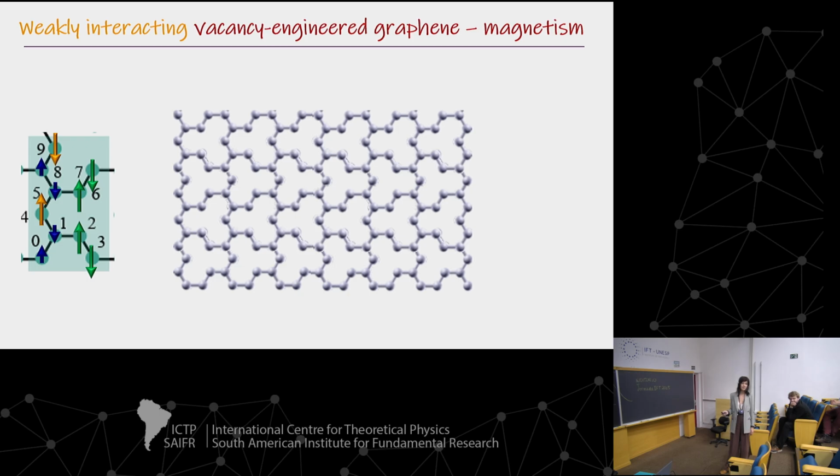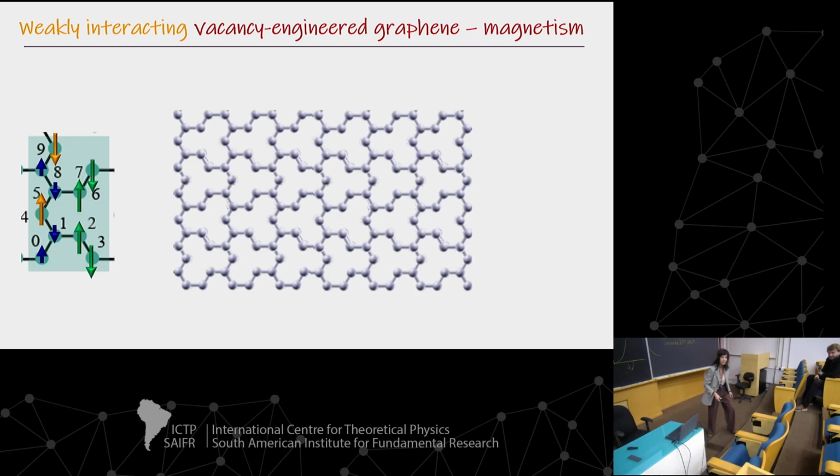But two questions on the modeling. I learned in school that carbon is 3- or 4-fold coordinated. And of course, it can be 2-fold coordinated as well, but this costs energy and some dangling electron and so forth. So in the modeling, I would have modeled this by having a change in the on-site energy at every site where I have a dangling bond. Did you do this? Yes. Okay, good. And the second, how do you know this number, basically? Yeah, well, there will be a number. It's just that it's not important for the symmetry argument. It's certainly not important, but it could be very important for the actual onset of the magnetic ordering itself, right?